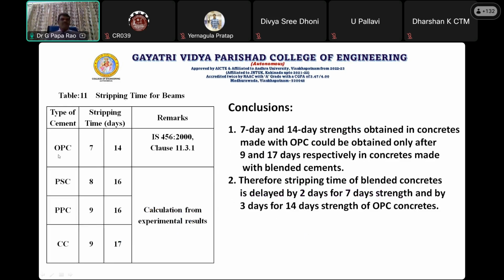Here, the stripping time for OPC is 7 days. And if you see PSC, slag cement, and PPC, Portland pozzolana cement, the stripping time for PSC is 8 days and PPC is 9 days, and again the composite cement is at 9 days, against 7 days for OPC. Similarly, at 14 days stripping time, our OPC is 14 days, and the other cements give the strength at 16 days and 17 days.